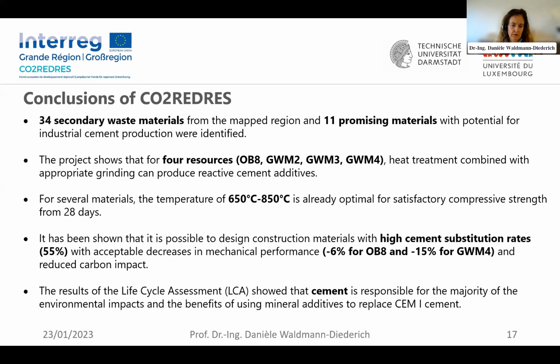Although we got not a high reduction in compressive strengths, so that we could come up to high substitution rates, which were about 55%, if we take into account that we accept a reduction in the mechanical performances of 6% and 15% for these two materials here, OB8 and gravel wash mud 4.